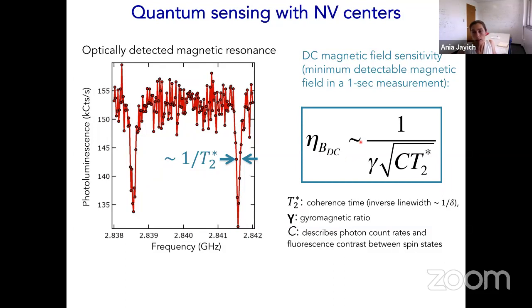And the sensitivity, let's call it the DC magnetic field sensitivity, which is the minimum detectable magnetic field, say in a 1 second measurement, is given by this expression, where importantly, the T2 star plays in here. The longer the T2, again, the higher the field sensitivity. Okay, so I just wanted to stress that coherence is an important element to sensitivity.